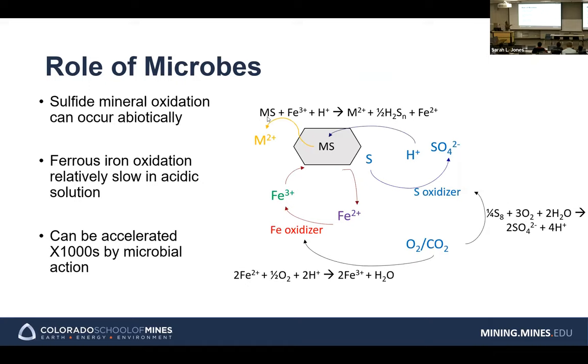So the role of microbes, I think it's a similar slide. Metal sulfide is oxidized and produces metal cation, and ferric ion oxidizes metal sulfide and produces ferrous ion, and the ferrous ion is oxidized to ferric by iron-oxidizing microorganisms, and then also sulfur produced from this sulfide, and a sulfur oxidizer oxidizes it to sulfate and at the same time produces sulfuric acid. So that's a very simple one-slide explanation of the bioleaching biooxidation. And as I said, these iron-oxidizing and sulfur-oxidizing reactions could happen naturally, but very slowly. But with the microbial action, we can increase the kinetics almost 1,000 times.